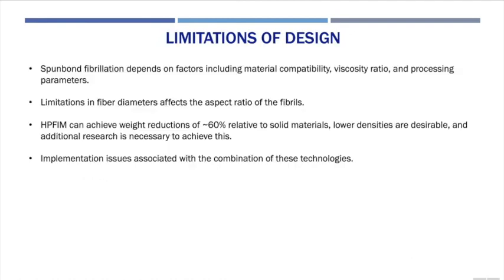However, the synergistic effect of the spun bond fibrillation technology and the high pressure foam injection molding technology with mold opening technique possesses many limitations. Firstly, the spun bond fibrillation technology alone has limitations in that the material compatibility, viscosity ratio, and processing parameters must be controlled to accurately produce fibers of good diameter so that we can have good mechanical properties.